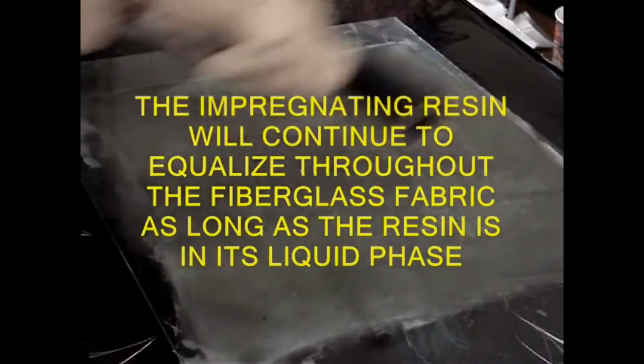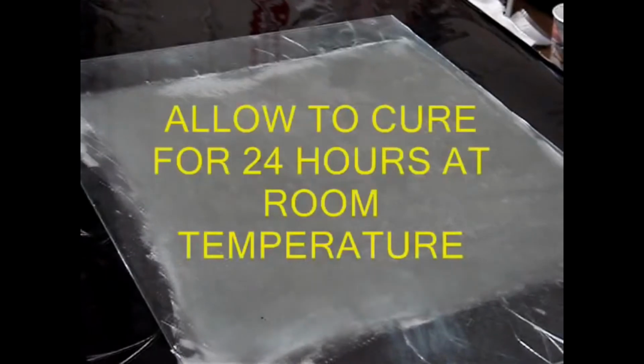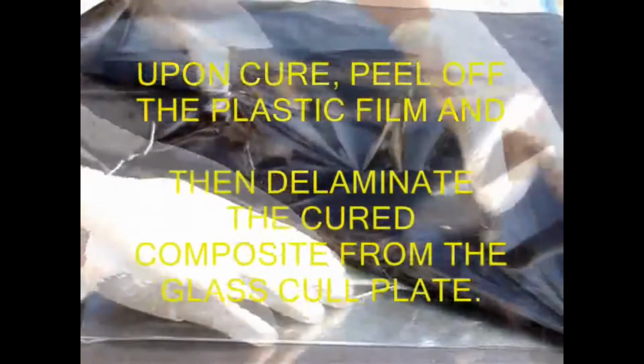The impregnating resin will continue to equalize throughout the fiberglass fabric as long as the resin is still in its liquid phase. And we have to allow it to cure for 24 hours at room temperature. Upon cure, peel off the plastic films and then delaminate the cured composite from the glass cull plate.